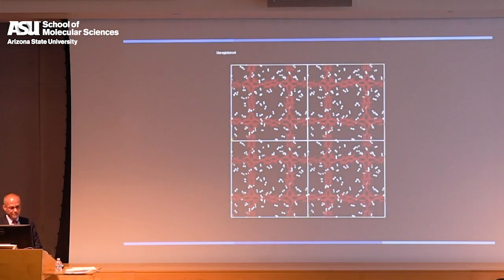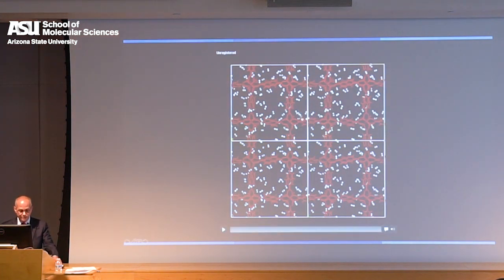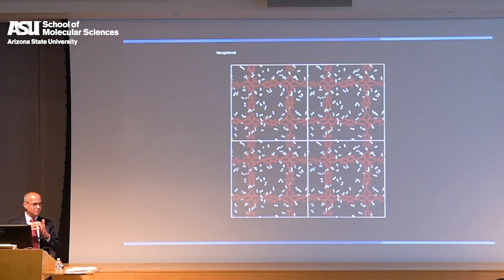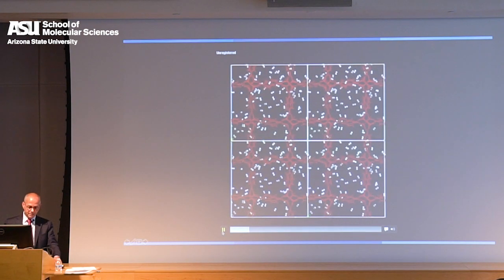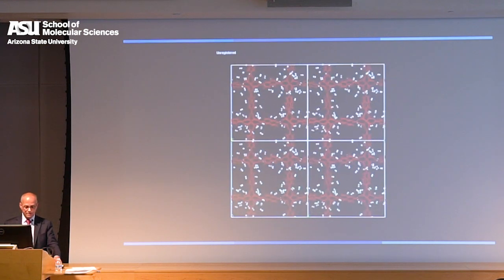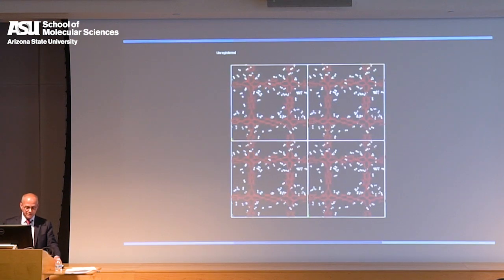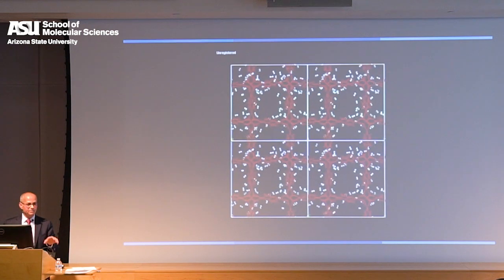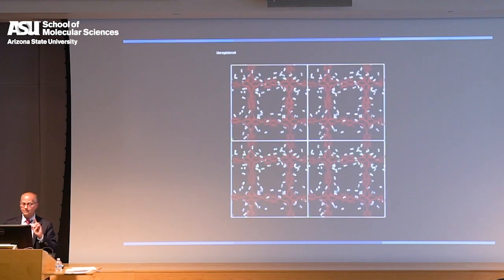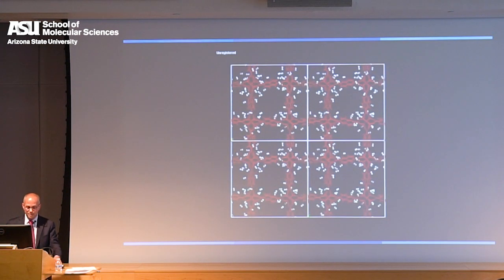Okay, so one of the things that we have done is hydrogen storage. This is a MOF in red, and the white spots are the hydrogen molecules. And the idea is that instead of hydrogen filling a very large volume, we create a MOF that could attract the hydrogen through electrostatic forces or polarization forces, and therefore you can pack it on its internal surface and therefore stack the hydrogen molecules like you would, let's say, stack cars in a car park. And here, you see how the hydrogen molecules are hovering in this computation, hovering around the MOF structure, and therefore you're able to store more hydrogen per unit volume with the MOF than without the MOF. Even though the MOF occupies its own volume, you still can store more within the MOF than without the MOF.